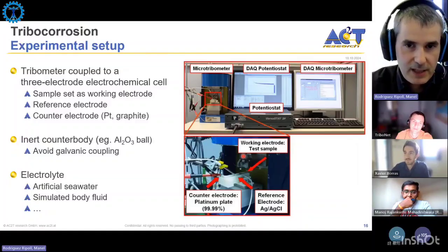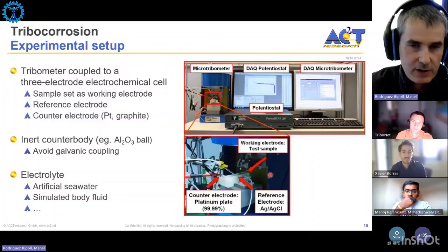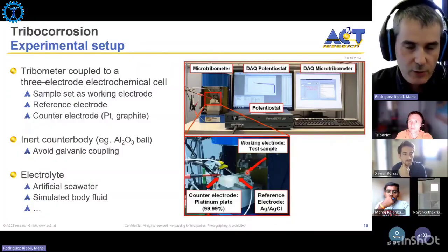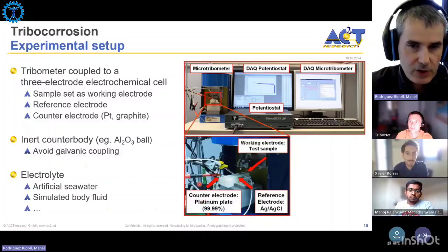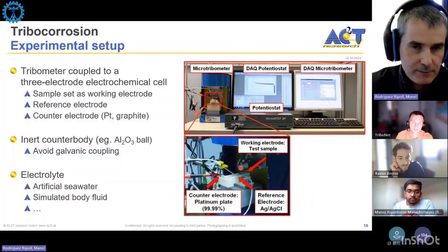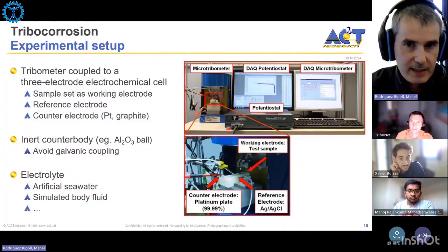In the electrochemical cell, we have three electrodes, or it can be two if you don't need to measure currents or apply any voltage. This three-electrode cell has a reference electrode, which is an electrode with a known and stable potential, to which all the potentials are referred. We have a counter electrode, which is a noble metal, typically platinum, or it can be graphite, for example, and the working electrode is our sample. This three-electrode setup is connected to a potentiostat that can measure the voltage or apply a certain voltage by triggering some current.